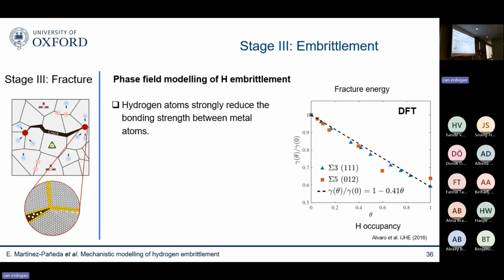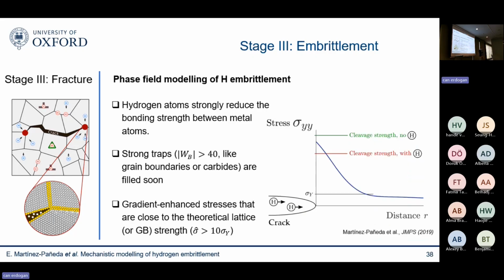And we have seen in atomistics that when we do that, we have a 40% reduction of the binding energy, of the grain boundary strength. So then the last question is, okay, what happens? Can you actually go from micro-void cracking mechanisms to brittle mechanisms just by lowering your grain boundary strength by 30 to 40%? And this is tricky because the grain boundary strength is 10 times the yield stress or so, right? So if you bring it to 6-7 times the yield stress, it still is quite a high value.